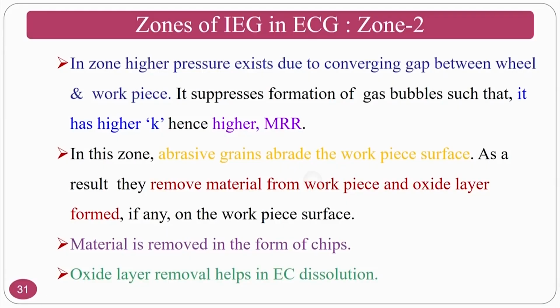In zone 2, higher pressure exists due to the converging gap between the wheel and workpiece. It suppresses the formation of gas bubbles and has a high value of K, hence the material removal will be very high. In this zone, abrasive grains abrade the workpiece surface. As a result, they remove the material from the workpiece and the oxide layer formed, and the material is removed in the form of chips also. That means oxide layer removal helps in the electrochemical dissolution.